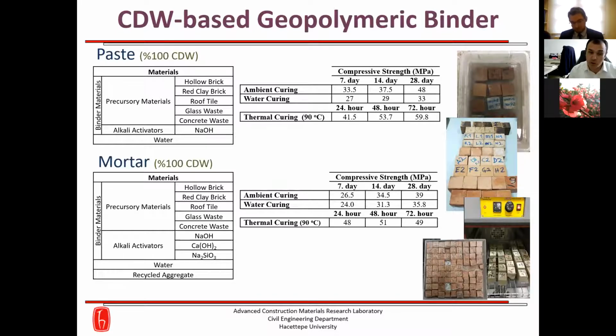After that, we produced the mortar specimens. We added fine recycled aggregate to the paste material, incorporating waste aggregates to the paste mixtures developed in the first stage for further recyclability. And different kinds of alkaline activators were tried in different combinations and at different rates. We obtained our best results at around 50 megapascal under 72 hours at 90 degrees centigrade thermal curing by using a ternary use of sodium hydroxide, calcium hydroxide, and sodium silicate as alkaline activators.